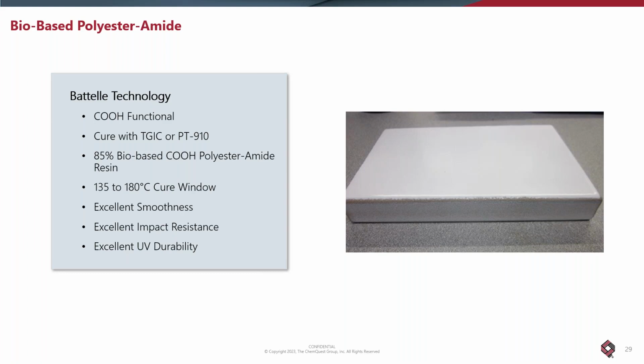It's a 85% bio-based carboxyl polyester. It's a long chain diacid that's been synthesized using high oleic soybean oil. It's like a C18, C19 type architecture. Anyway, this stuff can cure with TGIC down to about 135 C, and it gives some pretty amazing performance. It's relatively aliphatic. It gives excellent impact resistance, but the one thing that I didn't quite expect out of this project, it gives some pretty incredible UV durability as well. And it's probably not as surprising as it should be, because it's a relatively aliphatic polymer. So that's something you can think about.